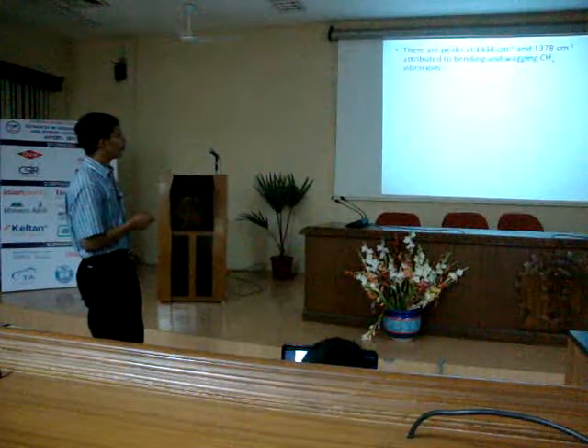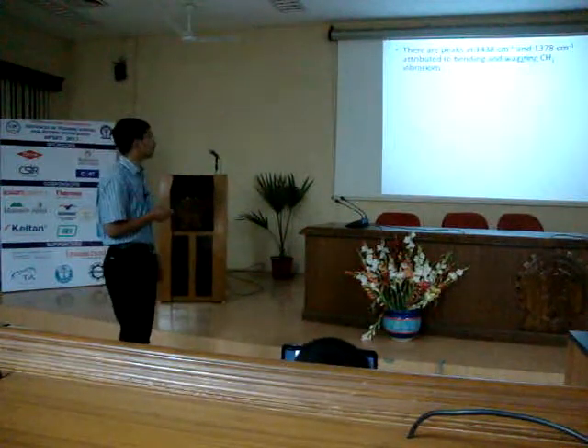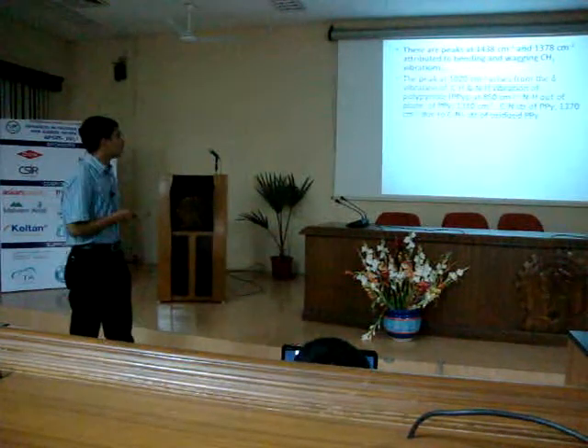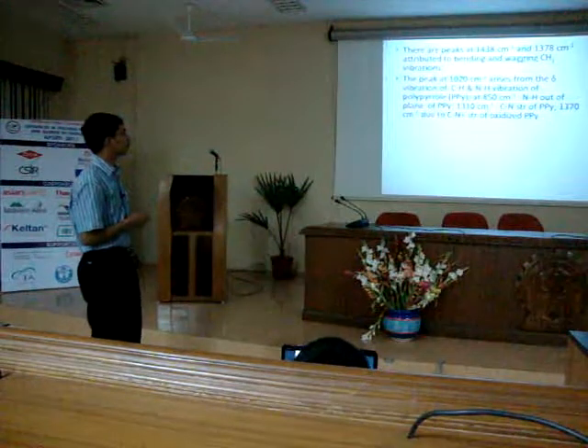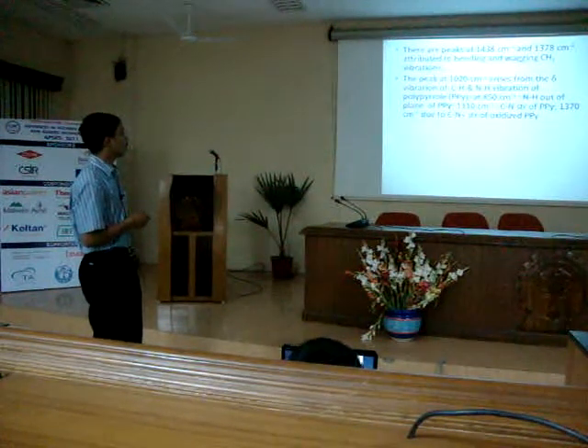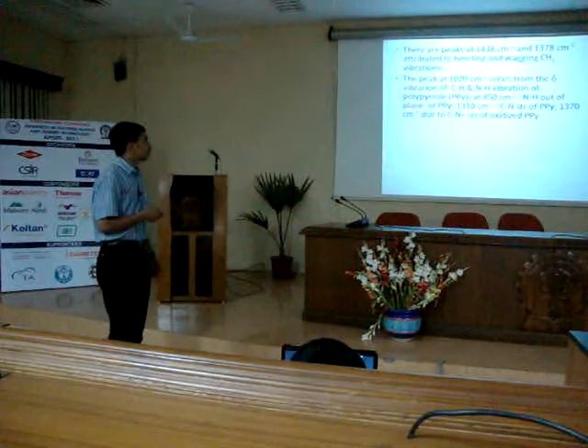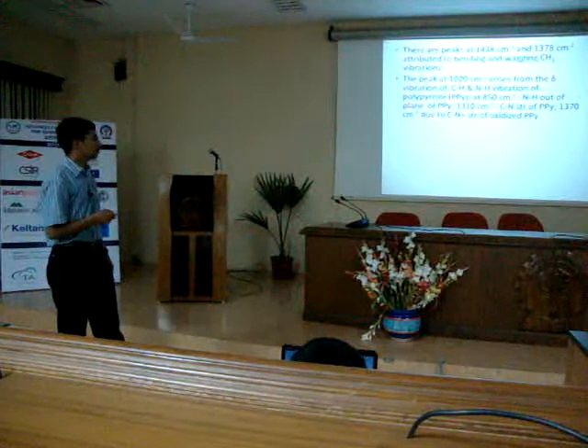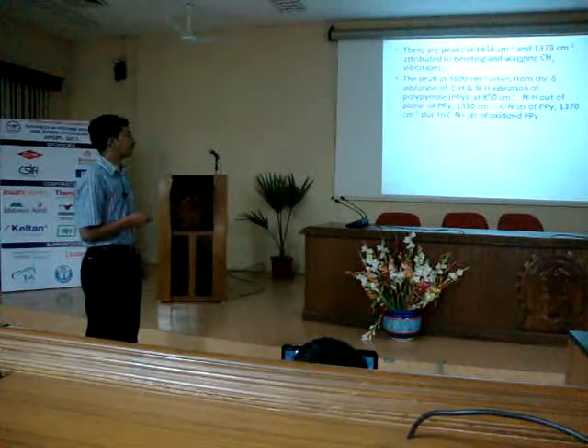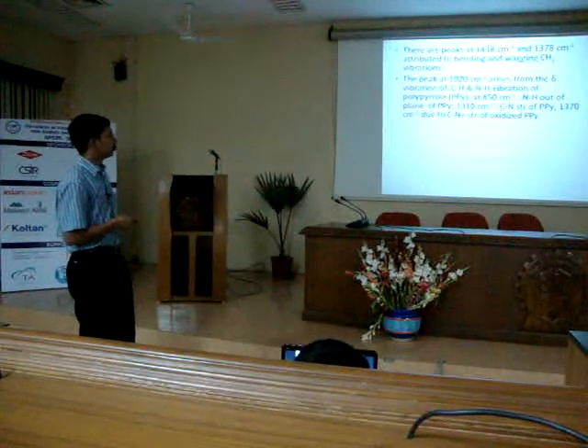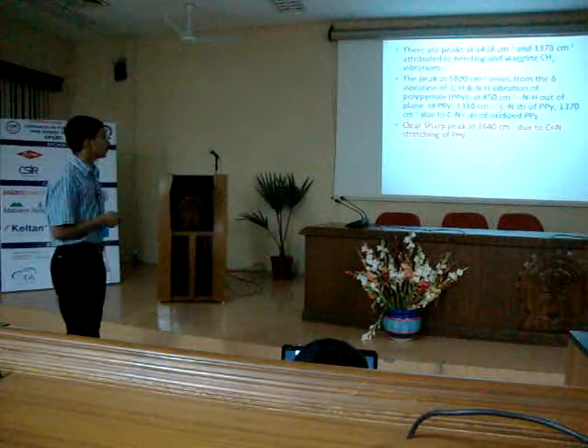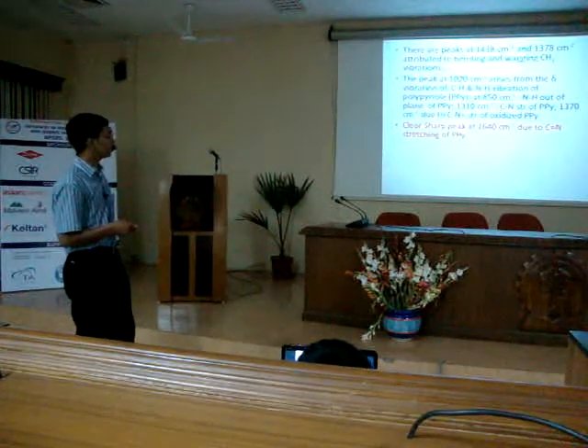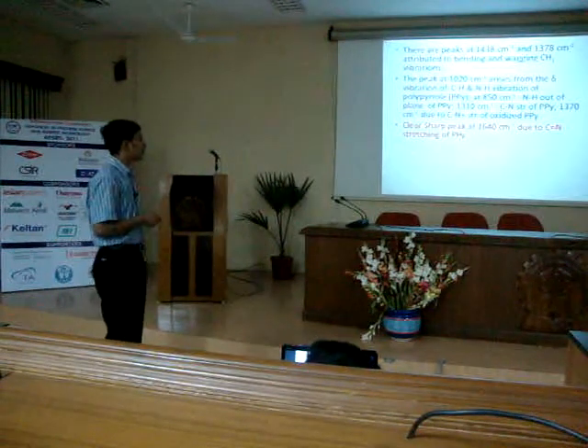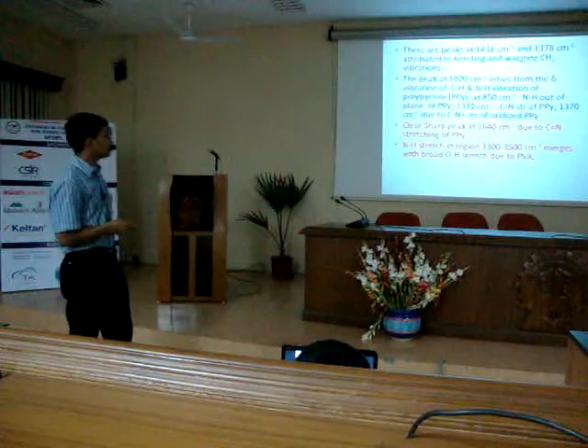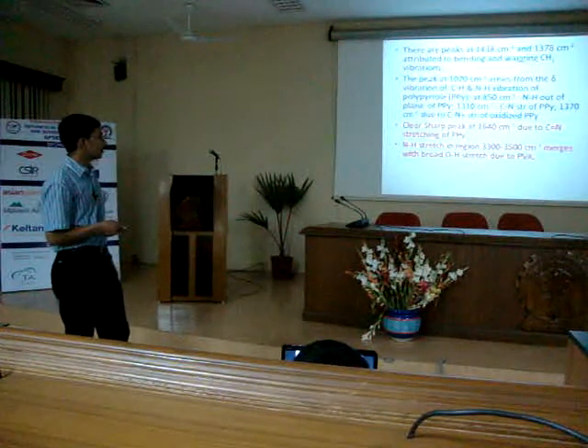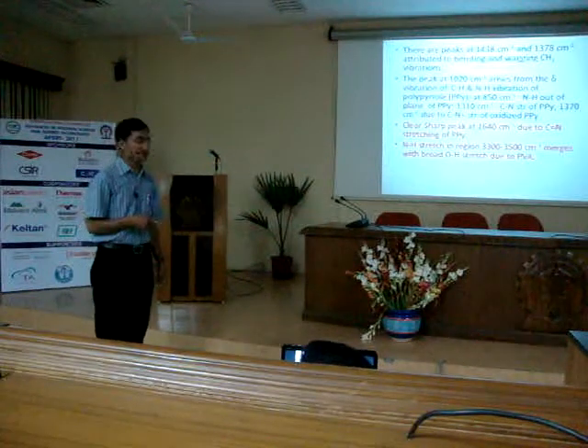There are peaks at 1438 per centimeter and 1378 per centimeter attributed to bending and wagging CH2 vibrations. The peak at 1020 per centimeter arises from the delta vibration of CH, and NH vibrations of polypyrrole at 850 per centimeter. NH out of plane of PPY at 1110 per centimeter, and C-N stretch of PPY, and 1370 per centimeter due to C-N+ stretch of oxidized PPY. A clear sharp peak at 1640 per centimeter due to C=N stretching of PPY. NH stretch in the region 3300 to 3500 per centimeter merges with the broad OH stretch due to PVA.